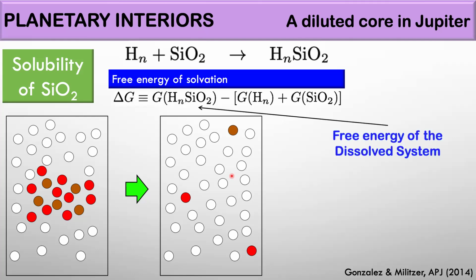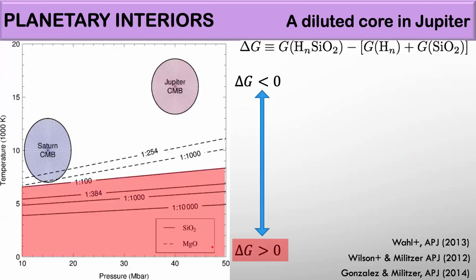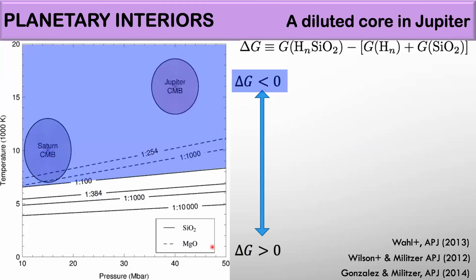The first term in this equation is just the Gibbs free energy of this dissolved system. And the second term is just the energy of the parts, hydrogen and silica. And the only thing I want you to take from this is that if this thing is negative, the thing dissolves. Okay? So I just want to compute this Gibbs free energy difference between these two systems. And whenever it's negative, it means that the dissolution of silica is favored energetically. So this is what we found. Below here, all the values of delta G are positive, and above here, all the values of delta G are negative, which means it dissolves.